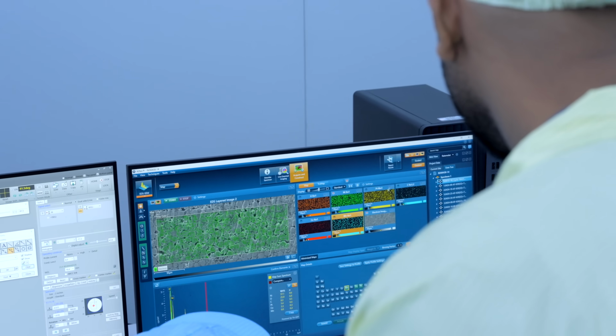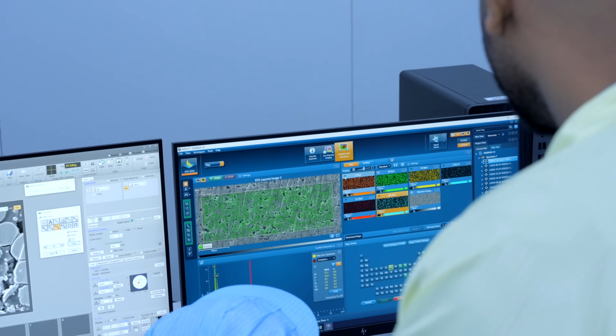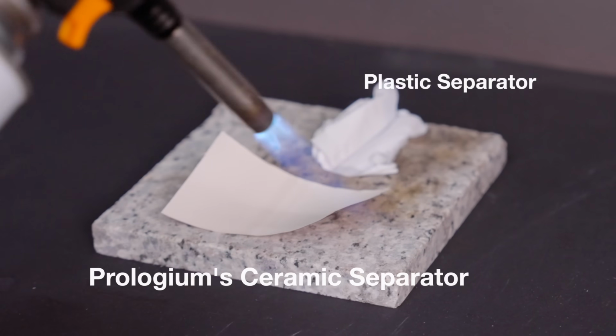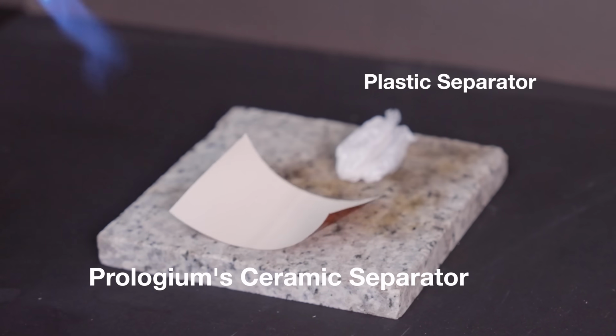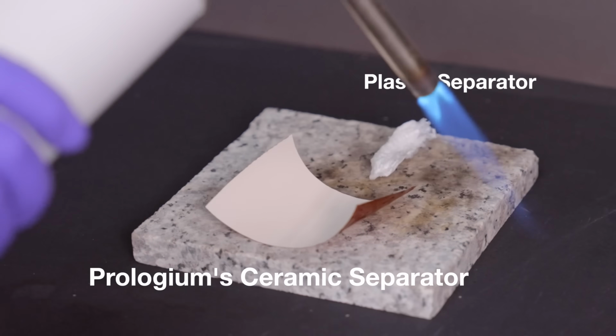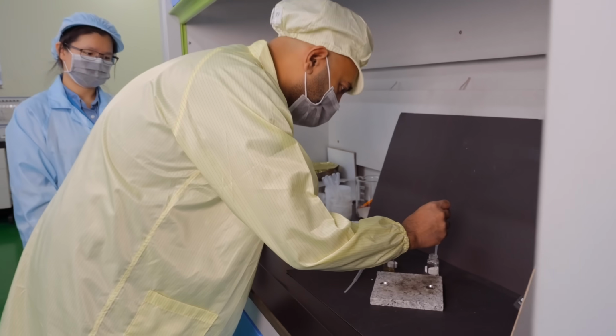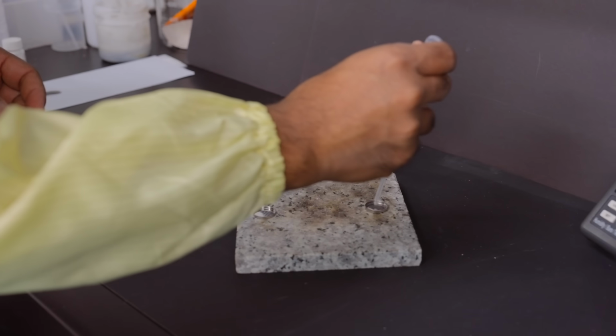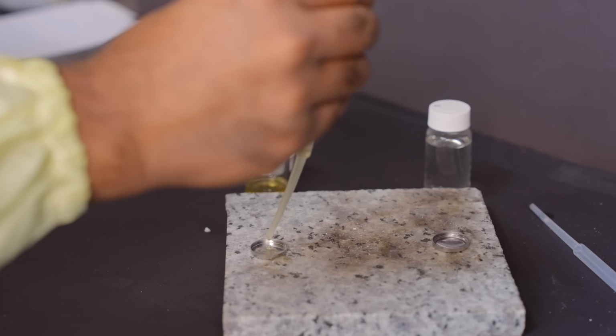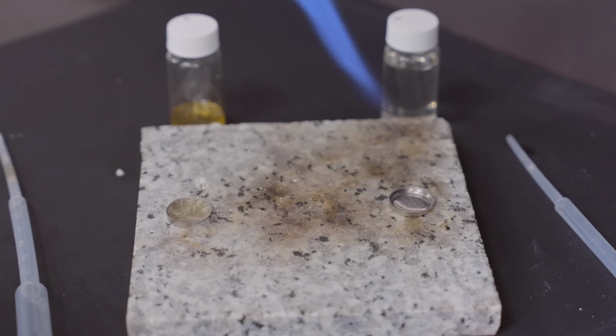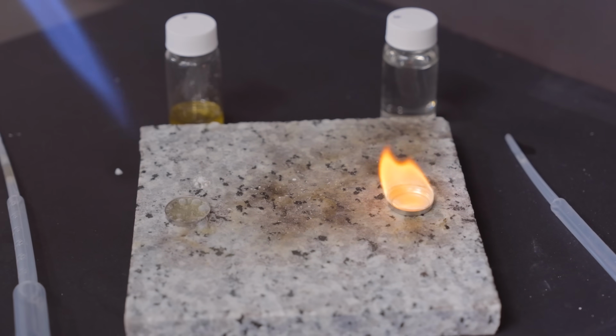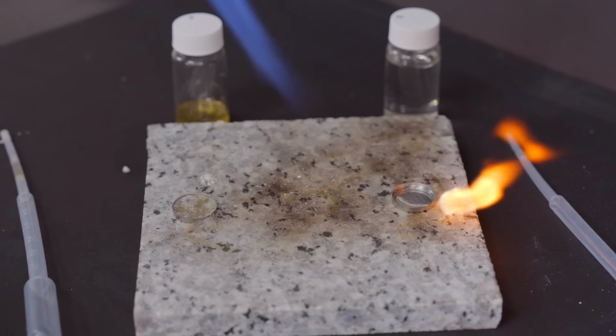ProLogium's answer is what founder Vincent Yang calls triple safety, 3 independent defenses, each backing up the next. Safety 1 is the ceramic separator. Instead of plastic, it's an oxide ceramic. It's hard, mechanically tough, and stable up to 300 degrees C. Safety 2 is the all-inorganic electrolyte. No carbonate solvents and no flammable organic chemistry of any kind. It's non-flammable not because it's well contained, but because the material itself can't burn.